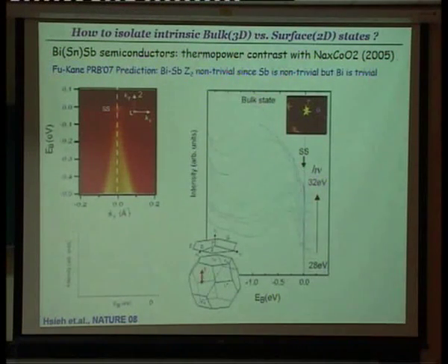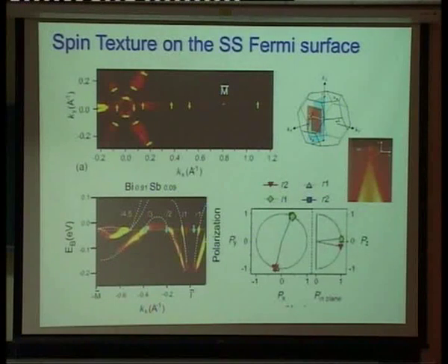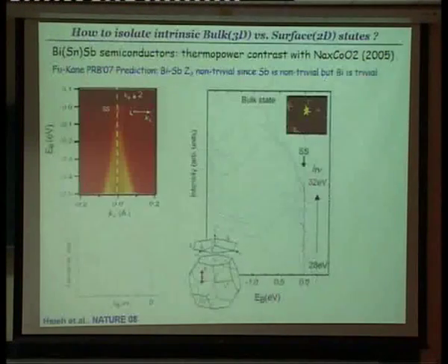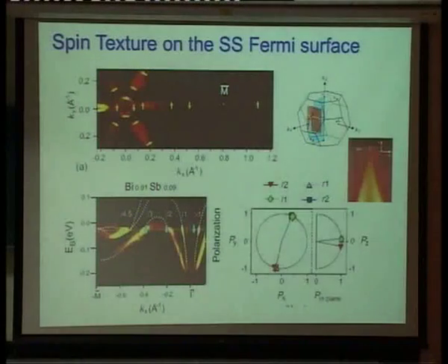But then we decided to look at the spin, because then it will become clear whether there is a Berry phase on the surface or not. Without that, we cannot identify the topological invariants. So what we did is that when you look at the satellite pockets, we see that only at the Kramers point, the time reversal invariant point, do you get the polarization rotating tangential to the Fermi surface.